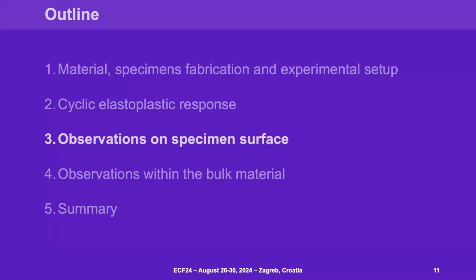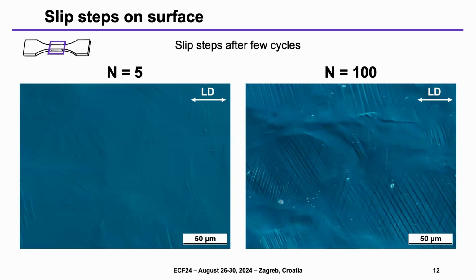Okay, so concerning the microstructural observation, we started by observing the surface of the flat specimen using optical microscopy. As you can see here, just after 5 cycles, some slip steps are present on the surface of the specimen. And with increasing the number of cycles, the slip steps become more evident, and also the quantity increases. However, using optical microscopy it is difficult to describe the morphology of these slip steps. So we also perform SEM analysis on the same surfaces.